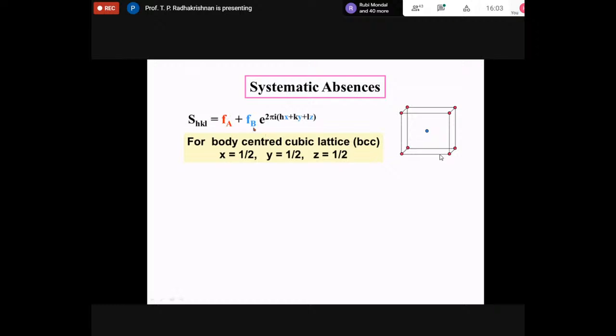And for B, there will be some Fb, its atomic scattering factor, with Hx, Ky, Lz, where x, y, z values are known. So let me substitute those values. So if I take this factor called the phase factor, 2 pi i into Hx plus Ky plus Lz, x, y, and z, I substitute half because this is like a BCC lattice. What will I get? I'll put half, half, half here. Half and 2 will cancel out. I'll get pi i into H plus K plus L. So the structure factor equation will be Fa plus Fb e to the power pi i into H plus K plus L. Now, this is a very interesting equation.